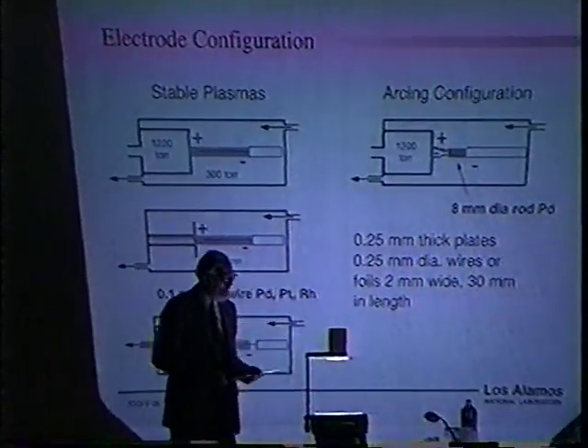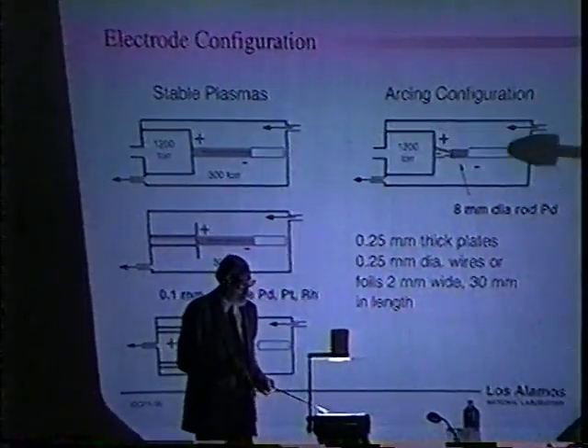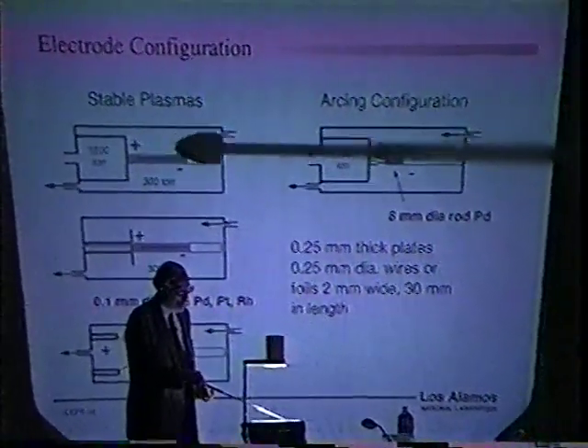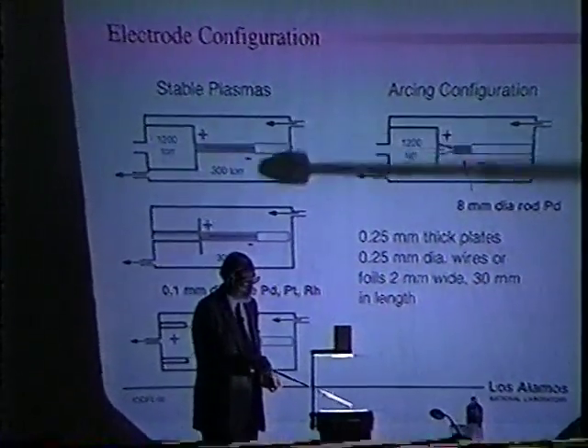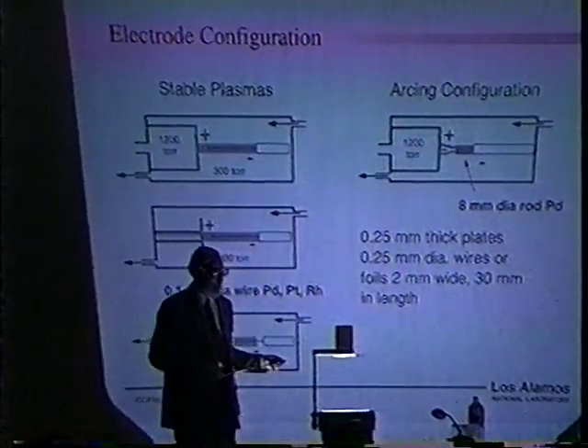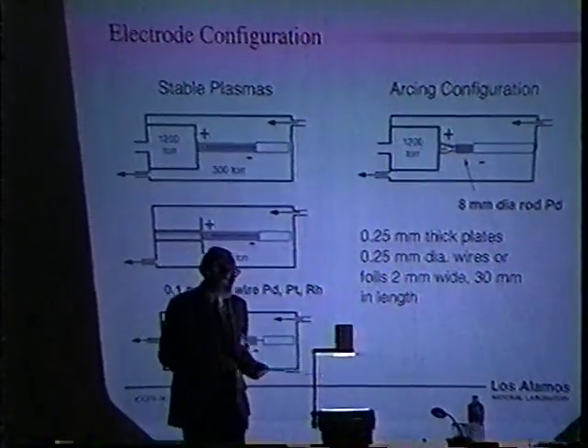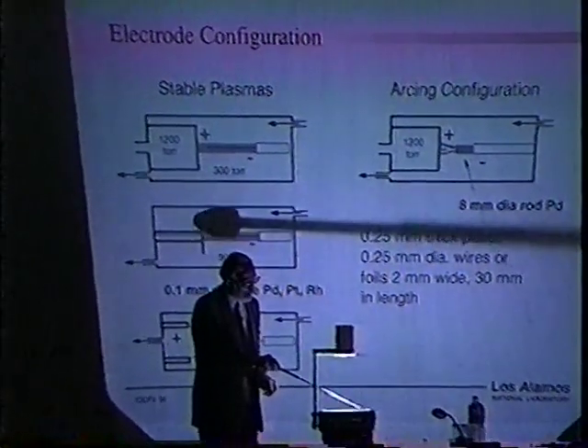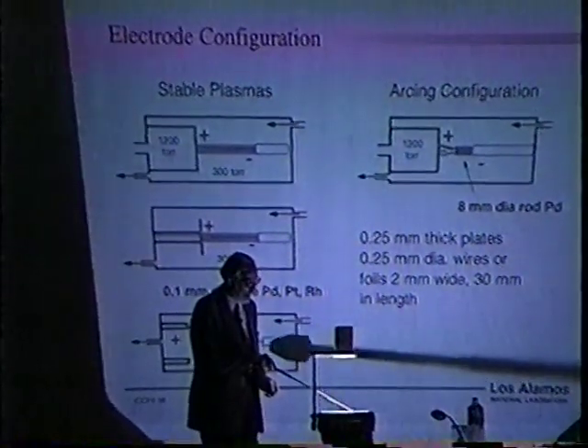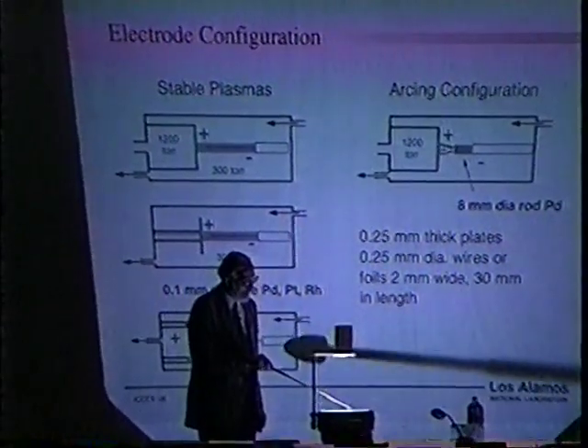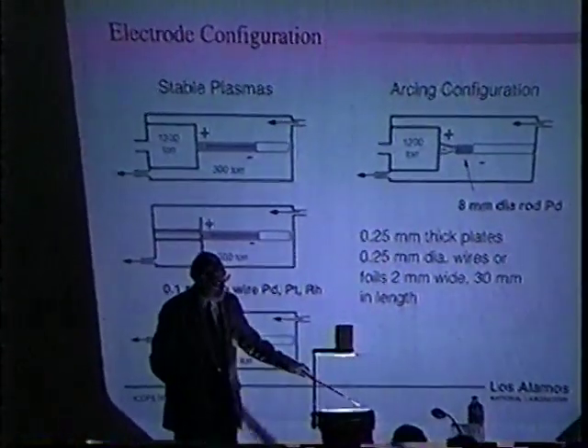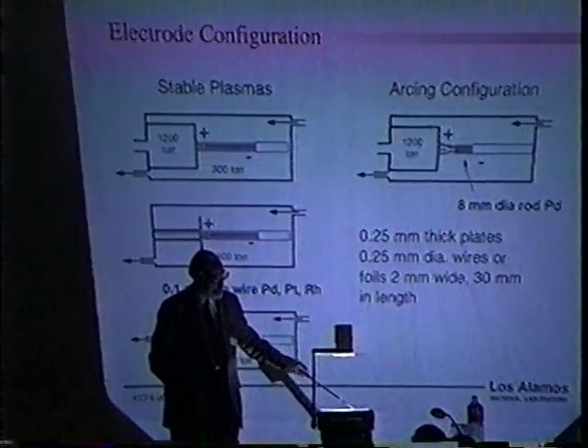The discharge looks like this. He's tried a number of variations. This is an arc discharge, which didn't work very well at all. This was the first variation, where there's a thin wire and a plate, and the discharge takes place between those two with gas pressure backing the plate. That did in fact produce tritium. They did away with that, using a plate now without the gas behind it. That wasn't quite so successful. Now the present technique consists of a wire of palladium as the cathode, and then a discharge. And the crucial point is that the discharge conditions need to be such that it does not extend up to this insulator. That was the flaw in this case.